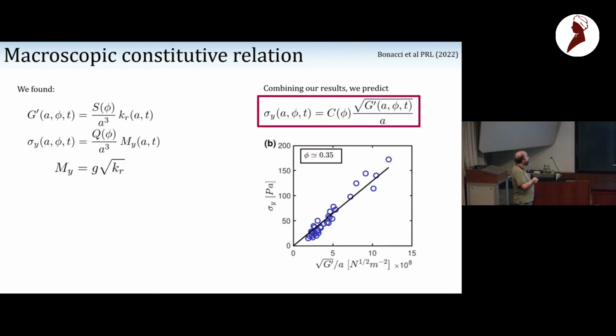And now, if you know that the rolling limit of contacts is a square root of the stiffness of the contact, and you have this relation between Kr, I mean the stiffness, and the bending limit, and here the macroscopic modulus and the yield stress, then you expect to see, parameterized by time, a relation between the yield stress and the Young's modulus. And this looks like it works pretty well. So basically, in this system, we have a scenario where the aging of the problem is entirely controlled by the evolution of contact.